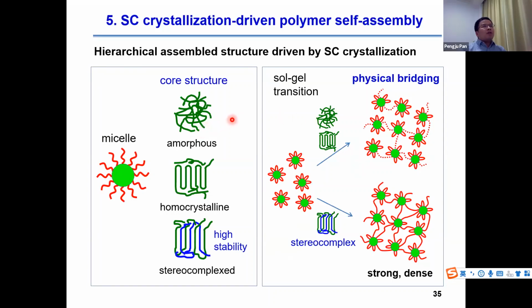For example, for the block copolymer micelle, if the micelle core is crystallized or co-crystallized, the micelle would have different size and stability. For the copolymer micelle in high concentration solution, if the hydrophobic blocks are crystallized or co-crystallized, the micelle solution can form strong and dense physical cross-linking through crystallization-driven chain exchange.